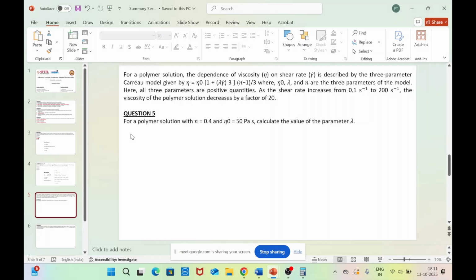It is written that if the shear rate is increased from 0.1 second inverse to 200 second inverse, the viscosity of the polymer solution is going to decrease by a factor of 20. Now for a polymer solution with the value of n equals 0.4 and eta naught equals 50 Pascal, calculate the value of the lambda parameter.